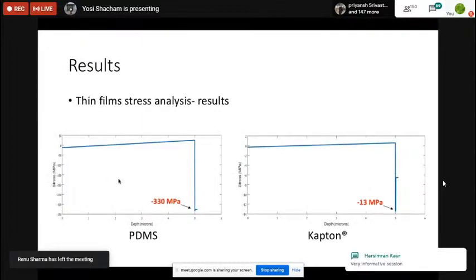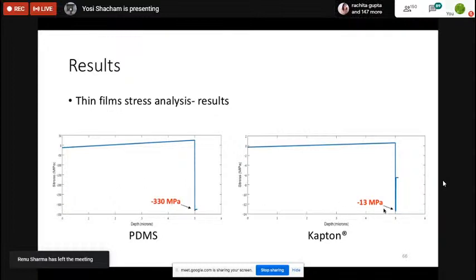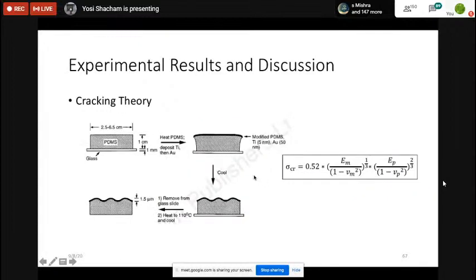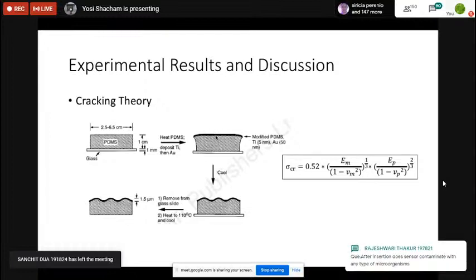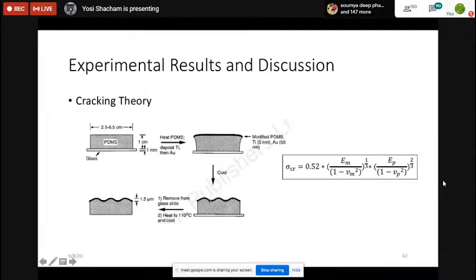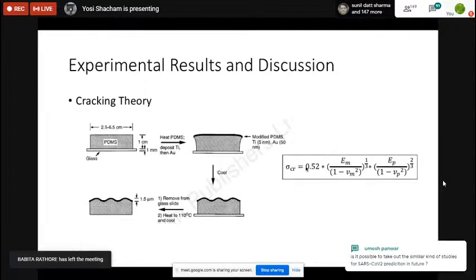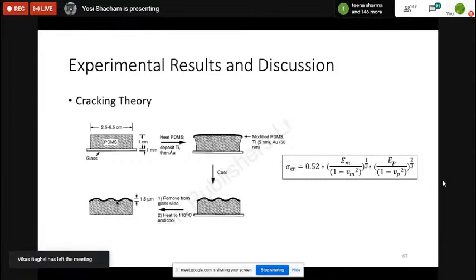And we did the calculation again and found out that for Kapton, the stress is only 13 megapascal, and the stress dropped significantly. And just to give you the mechanism of cracking, if you have a PDMS, you put the metal on top of it, and when the device is cooling down, this is applying a force, and you have something called wrinkling. It's a non-linear phenomenon, and this is the critical stress for wrinkling. This is taken from a textbook, and these wrinkles break here on the bottom of the metal.